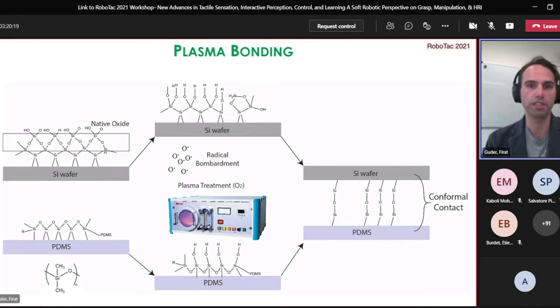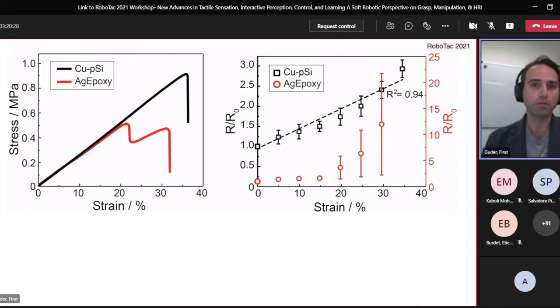So this is called the condensation reaction. Again, it's not too important, but all you need to know is that it's a very robust contact. The figure on the left shows the strain-stress curves, where we attach wires on both ends of the sensor, one with the copper porous silicon composite contact, and the other one is just with silver epoxy.